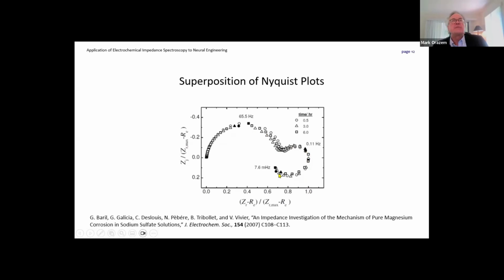Again, showing that what's happening here is that the chemistry was not changing. What was happening as a function of time was effectively the same, but the active area was changing because of the formation of an oxide.